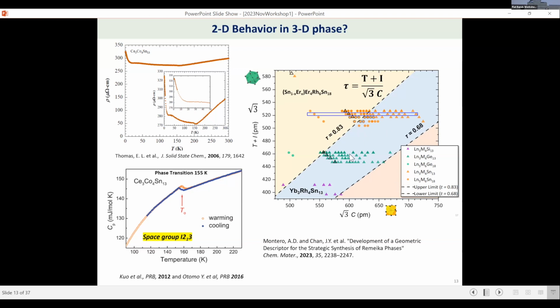But bottom line is, he made a map where we said, okay, depending on the size of the lanthanide, something as simple as that, and the distortion, T represents the height of the trigonal prismatic unit, and I represents the icosahedral, the size of the icosahedron. Yeah, and he made this new tolerance factor, similar to what people in the perovskite community have done,